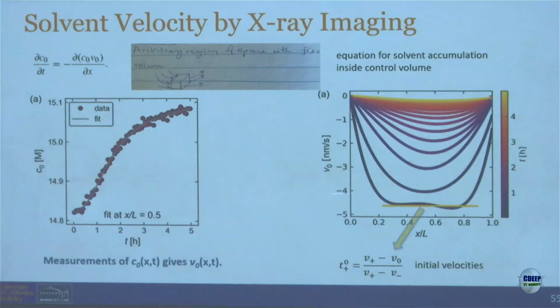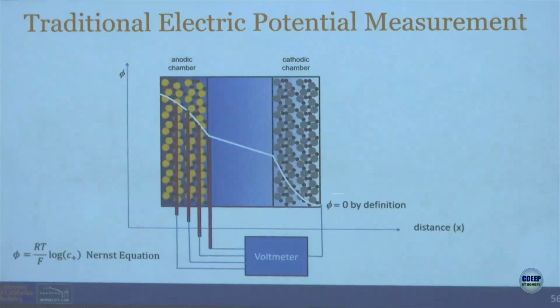Okay. And so, to my knowledge, this is the first time the solvent velocity has actually been measured more or less directly, because you can't argue about that equation. The last thing I want to say is that when you have a concentration gradient, you must have a potential gradient. And so, in the simplest case, you can just put in Nernst's equation and take the logarithm of that and say that's the potential. So I'm imagining that you put a voltmeter with the negative electrode, and you have a lot of these electrodes in the electrolyte, and the question is, how is the voltage changing as a function of position?